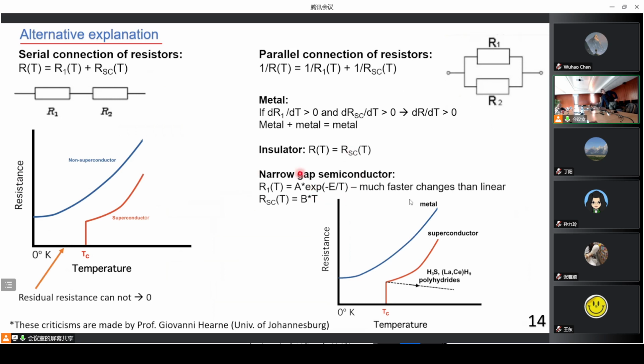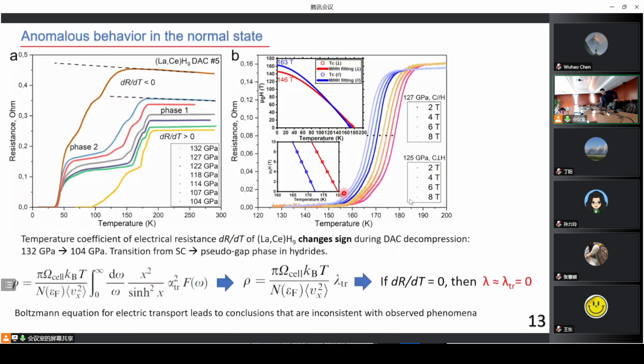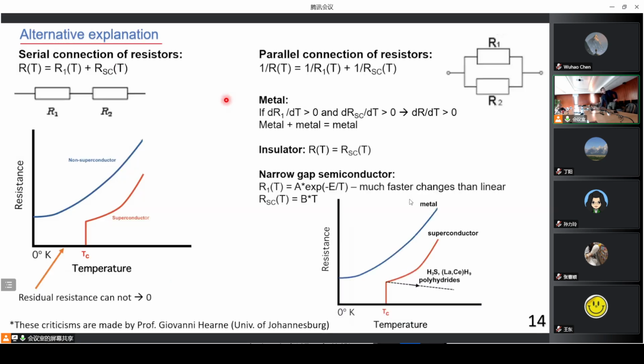In this case, the dependence of resistance is very nonlinear, exponential, and when we use summation, we will not see a linear dependence of resistance on temperature, but we see exactly linear dependence here. It's just a straight line, just plain dependence, no dependence of resistance on temperature. So in both cases, we cannot explain the phenomena which we observe. Again, this small picture just demonstrates my logic, and explains it once more.